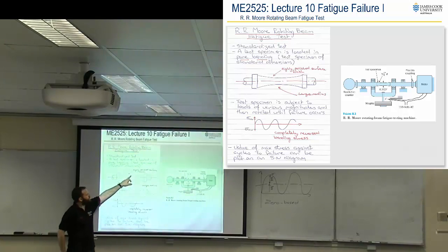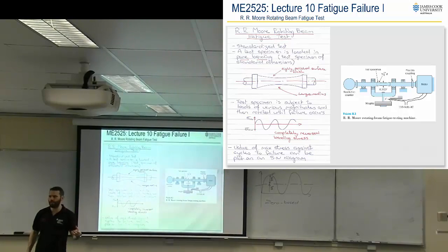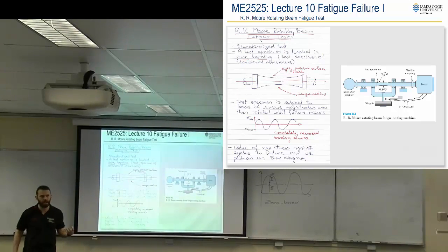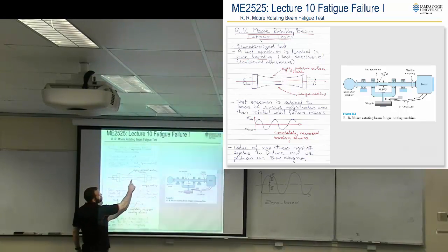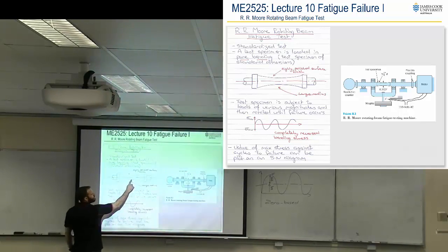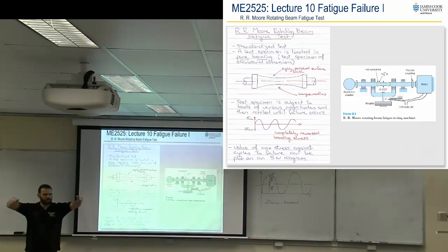really highly polished finish so that obviously you don't have any roughness or notches or anything like that that's going to cause the fatigue to happen prematurely. And you have this large radius here so that there's no notch, but you know full well it's going to fail in that center section there. So that's about the radius, and there's an Australian, at least an Australian, if not an international standard for what the actual profile needs to be. But that profile's been calculated such that the stress concentration isn't an issue, right?